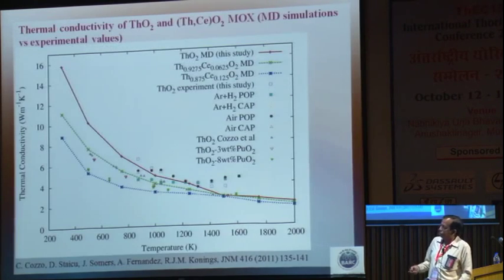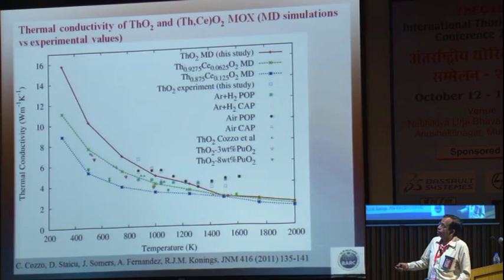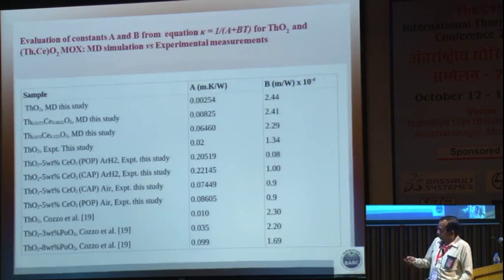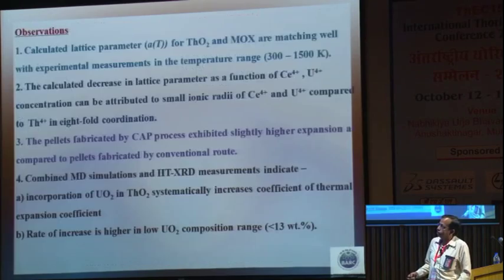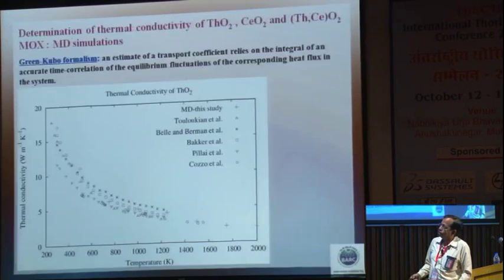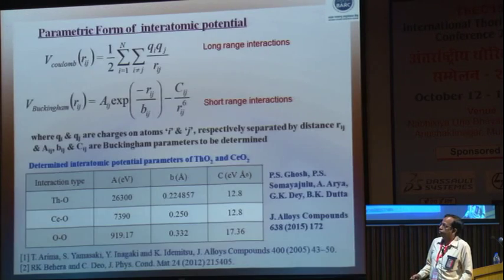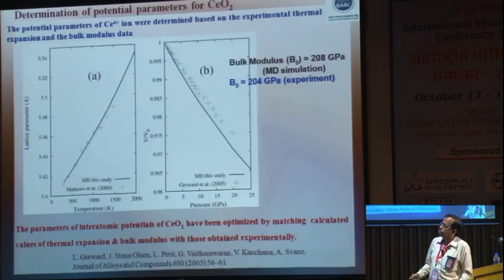Now, just the last part of my talk: thermal conductivity as evaluated by theory and by experiment, compared with simulation. In these plots, this is the thorium oxide MD simulated thermal conductivity, this one, and then you also have the experimental values along with that, and you can see that the variation between the two is minimal, and therefore one can substitute for the other. And the same thing is listed here in the form of a table with A and B, as I told you in the previous view graph. There is an equation here which shows the thermal conductivity as a function of temperature.